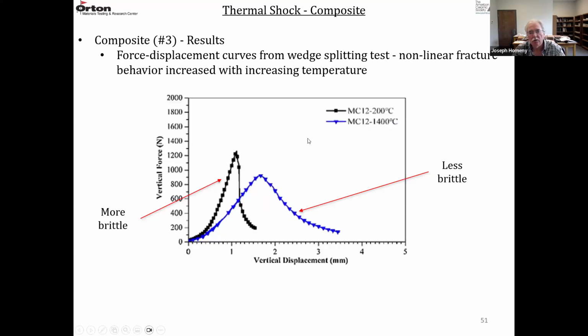And the same behavior for MC12. The black is at 200 degrees C curing. The MC12 in blue is after 1400 degrees C curing. So at room temperature, these tend to be more brittle. And as the temperature increases, they become less brittle or more ductile. So the more ductile they become, the more strain they can take, and the better they can resist thermal shock.